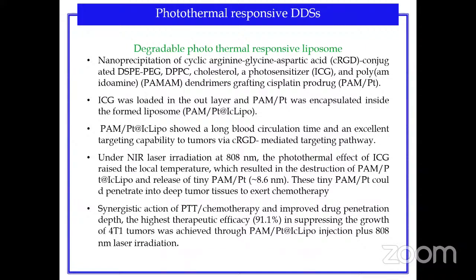Under IR radiation at 808 nanometers, the ICG raises the local temperature, which in turn disrupts the grafted dendrimers, and the release from the liposomes will happen. A tiny, nanometer-sized prodrug will be released from these systems. So these systems show us two points: one area which will enhance the temperature. That enhanced temperature will kill the cancerous cells, and the cisplatin will also kill the cancerous cells.